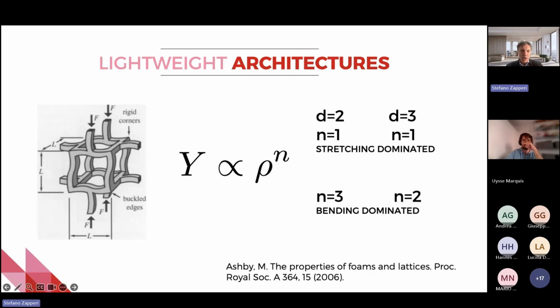The idea is to have objects that have a certain elastic property, like the Young modulus, which is typically the stiffness of the material, and you want them also to be very light, with as little material as possible. What they found by looking at structures of various types, foams and so on, is that the Young modulus typically scales with the density. The heavier it is, of course, the stiffer it is, and it does so with a power law. The power law was easy to explain at the time. When n equals 1, this means that elasticity is controlled mostly by stretching. So when you pull or compress, it's stretching that matters. On the other hand, when bending is dominating, then this exponent n becomes 3 in 2 dimensions and 2 in 3 dimensions.